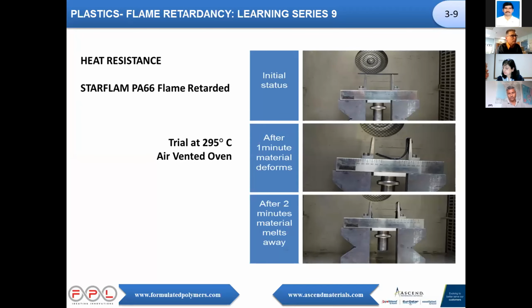So what can it bring practically to the product? Here you see a normal nylon 6/6 flame retardant. We place a specimen in an oven at 295 degrees C. It's still cold, you see nothing. After 1 minute, the material starts to deform. And then after 2 minutes, once heat takes up the plastic, it really melts away. Here you only have some drops of plastic somewhere.